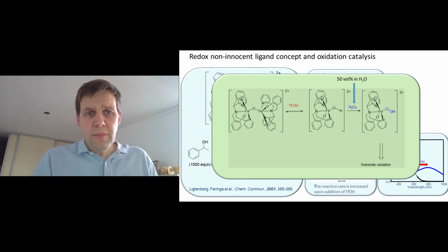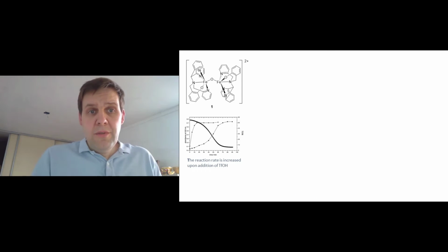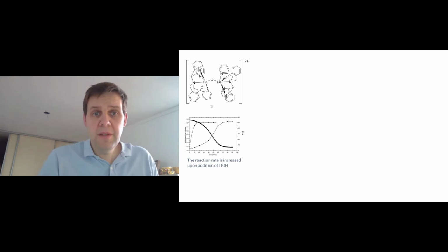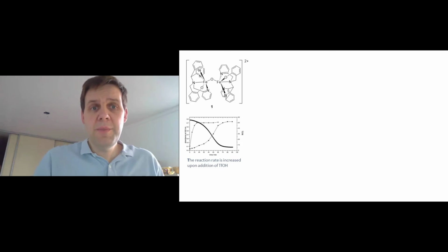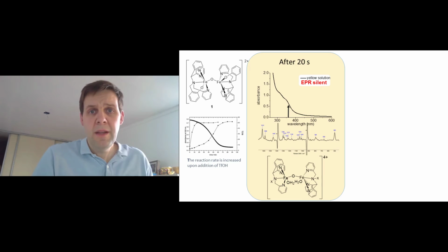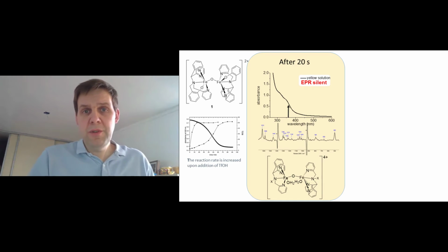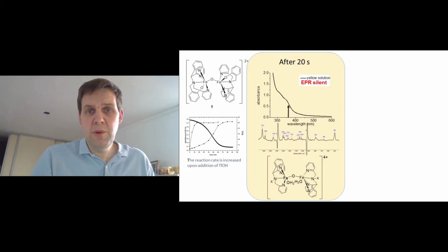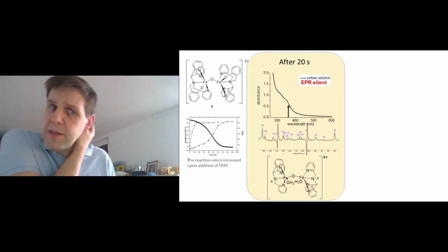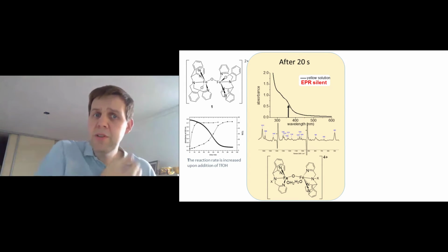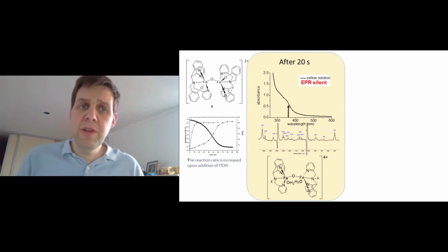So how do you study such a reaction? Well, probably the easiest thing is to follow the reaction over time and see how its spectroscopy changes. Now, if we follow the reaction over 20 seconds with acid present, we get this nice yellow absorption, which is essentially featureless. And, well, there's not really much we can do to study this compound because you can't isolate it from the solution. There's too many components in there and it's present at such a low concentration.